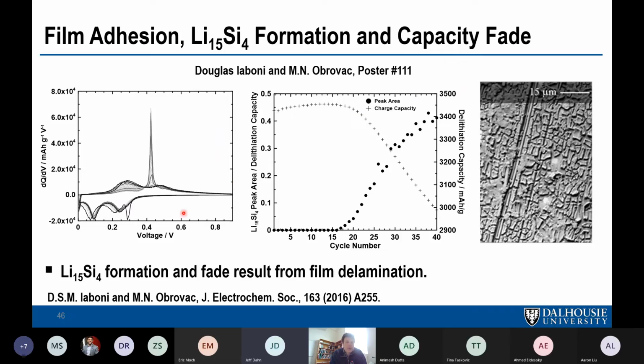And if you cycle a thin film and watch 15-4 growth, you can learn a lot about how these materials work. So you can see initially this is a thin film of amorphous silicon on copper foil, and its lithiation is initially over here at a low potential because it's stuck to the film. So initially you get the nucleation and growth peak here, and there's no 15-4 phase initially. And initially, this is the capacity here, and the capacity cycling is very good. And this is the area under the 15-4 peak, and initially you don't see any 15-4 peak because it's pinned to the film, and you get that stress voltage coupling.